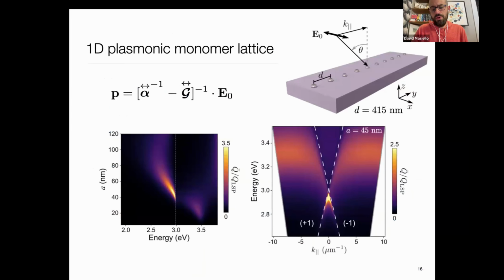So like before, in the first phase of our work, we went out ahead of experiment and did some theoretical work to try to predict the photothermal properties of these kinds of plasmonic lattice systems. The simplest case is just a 1D lattice where the interparticle spacing is 415 nanometers. And what we did here is we simply grew the radius of each particle in each unit cell. This is a Bravais lattice. And what we see here, on the color axis, is the absorption spectrum, or the absorption cross-section. A horizontal line here would be the absorption spectrum.